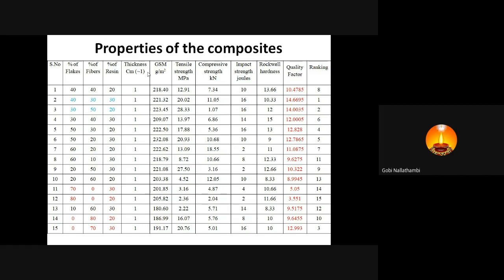Okay, right. So after making this quality factor and ranking, samples 2 and 3 are the best suited material for making a composite. If you see samples 14 and 15, sample 15 takes position 3 because higher, that is 70% fiber and 30% resin, can perform better than the samples of this one. Okay, so there is no fiber, only flakes. So here the performance is very poor, samples 15 and 14. So when we are increasing the composition of the fiber, then we will get a higher quality composite, right?